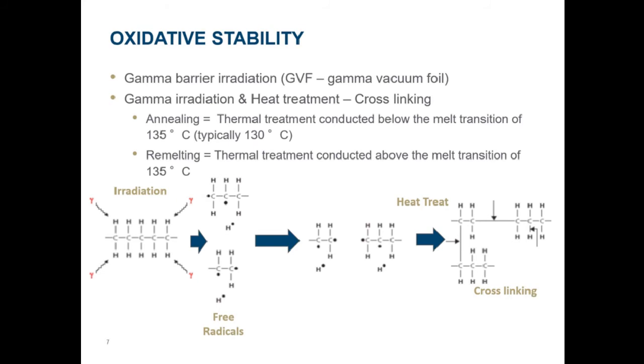Another way is annealing. It brings the material to a temperature just under its melting temperature. Increased thermal energy results in increased molecular motion. The increased motion of the polymer chains helps promote additional reactions between free radicals. However, because the crystalline regions have not melted, the polymer chains do not have unrestricted mobility, and thus not all of the free radicals are eliminated.